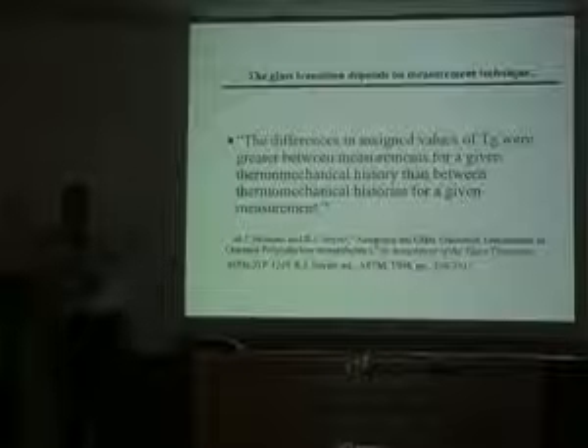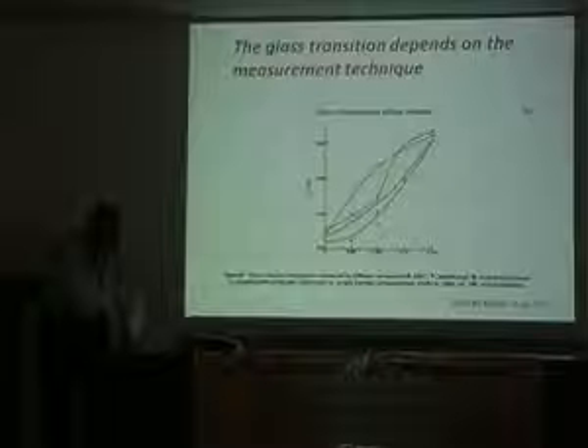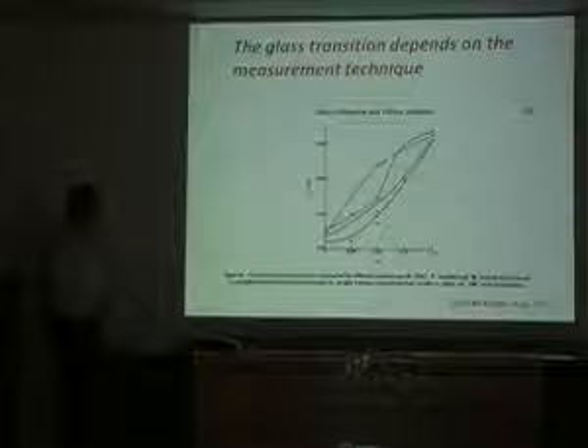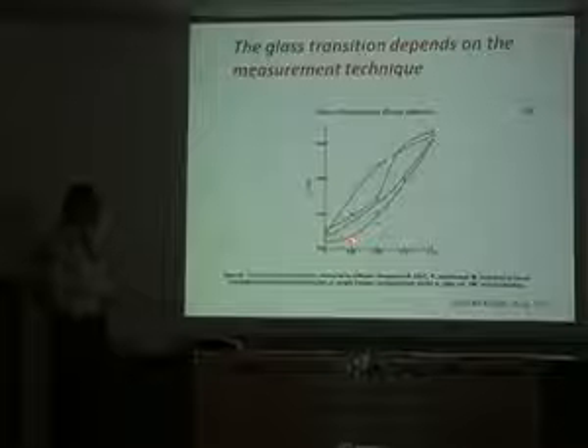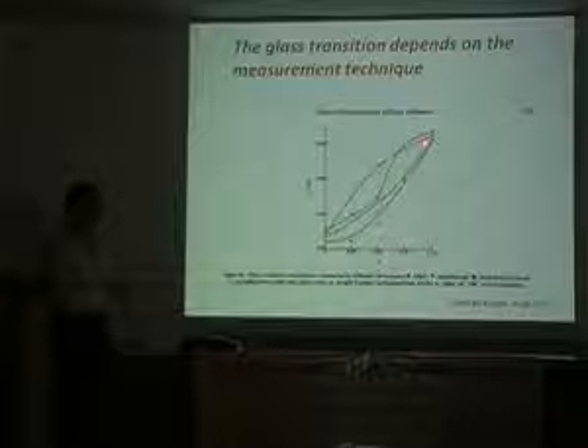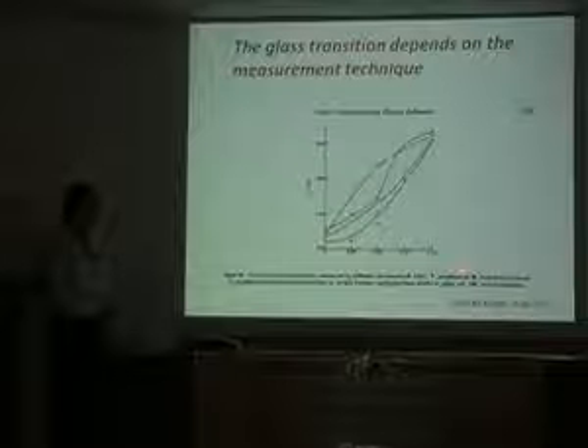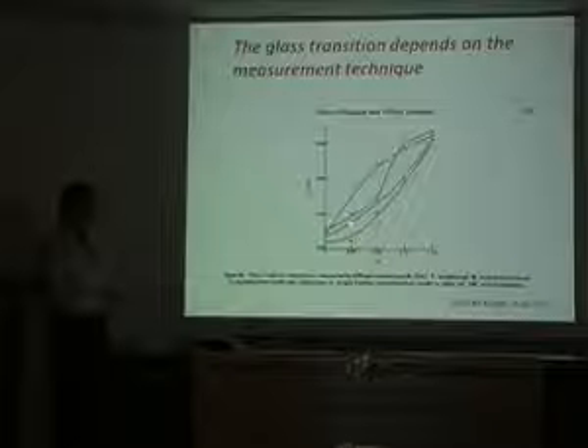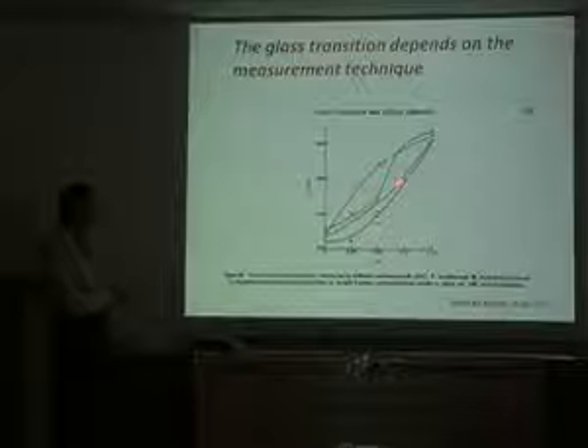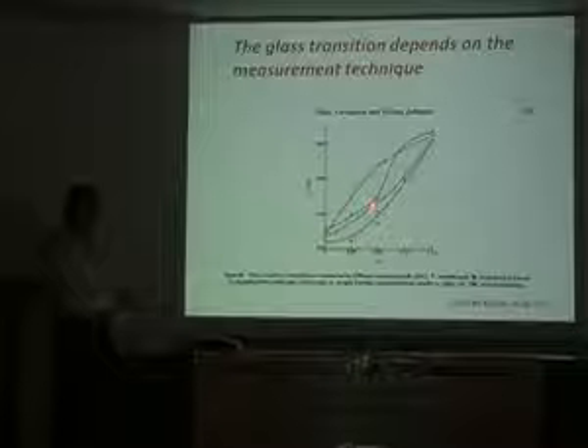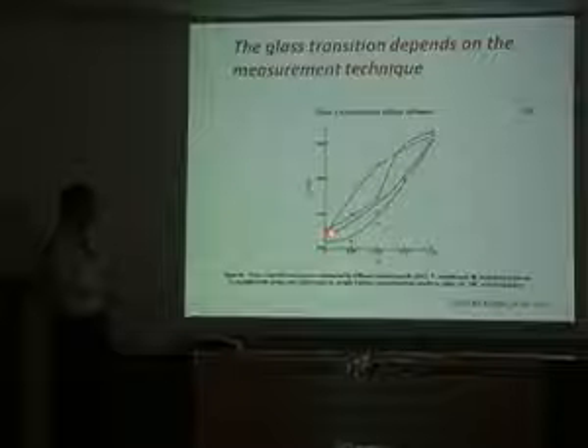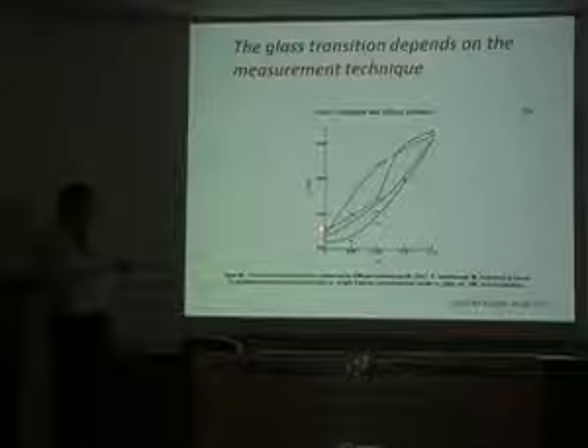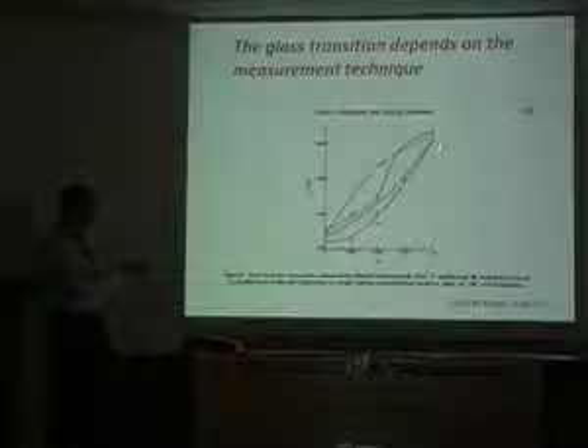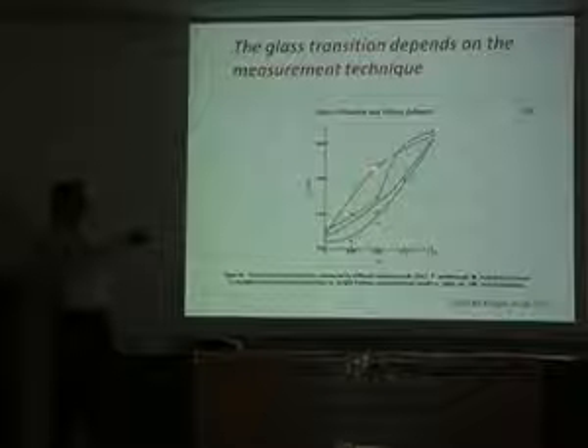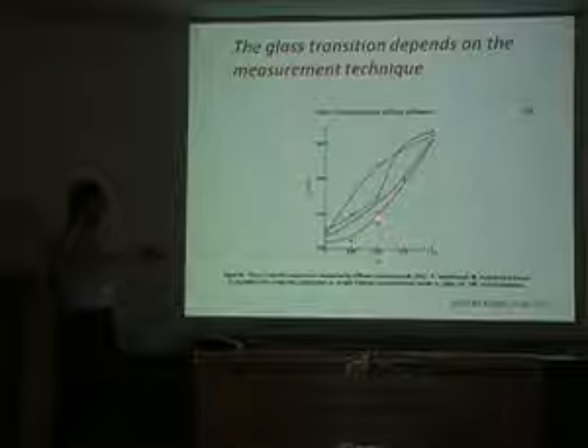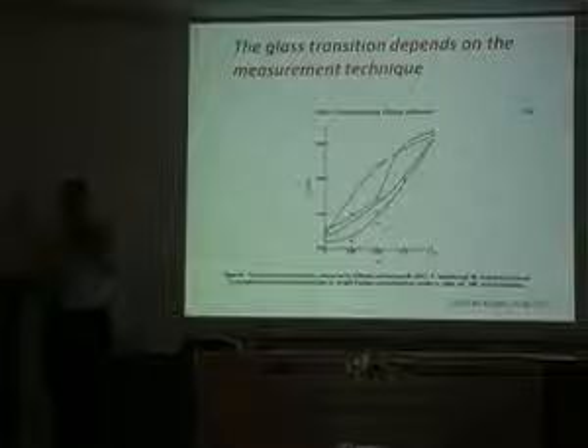by a dynamic mechanical measurement, they're going to be quite different, and they can be quite complicated in some systems. This is a TG plot versus weight fraction of a polymer blend, and here the circles are differential scanning calorimetry. The upside down triangles are some sort of dynamic mechanical measurement. And you can see even with the different dynamic mechanical measurements, you get different results. I don't know which one was tangent delta and which one was G double prime, but they're different. And then there are dielectric measurements, which in this instance are sigmoidal, as opposed to having a smoothness to the curve. So it's an important point. If somebody reports the TG here, it's 180 or 190, and down here with this measurement it's below 140. So you can get very big differences. At least it's something to be aware of as a practical matter.